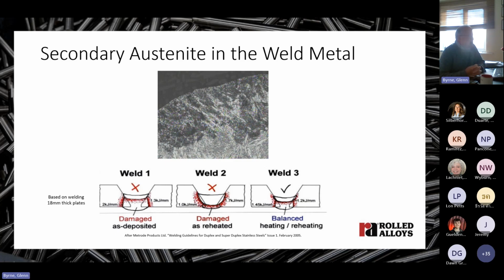So control of heat input and interpass temperature helps a lot to minimize this effect, but good welding technique helps too. Welding parameters that give a substantial thickness of first pass, followed by a second pass with a heat input about 20% lower than the root run, avoids reheating of that part of the root that's exposed to the environment. That's here. So the corrosion resistance is improved, and we call this the cold pass technique. Now this schematic is shown for 18mm thick plates, but it illustrates what we're trying to achieve. A decent size root run, reduce the heat input to the second pass, minimize the reheat treating of the root, and get good properties, unlike these other two cases.